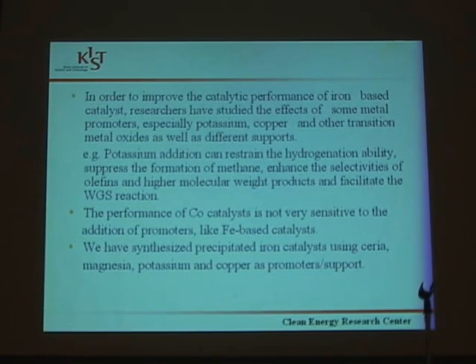The performance of cobalt catalyst is not very sensitive to the addition of promoters, like iron-based catalyst. In the present study, we have synthesized precipitated iron catalyst using cerium, magnesium, potassium and copper as promoters or support.